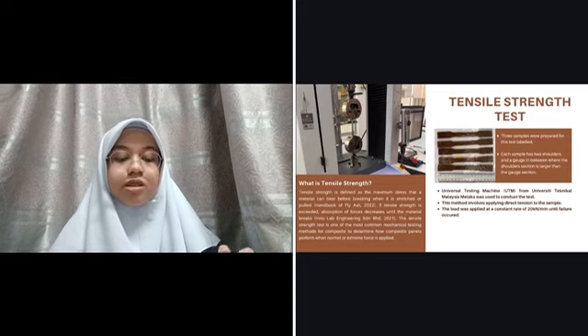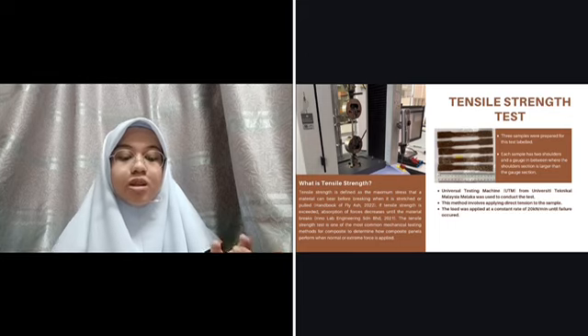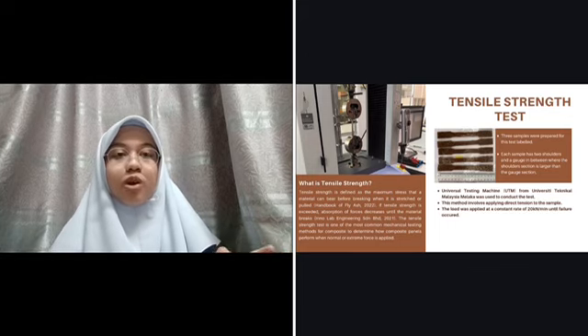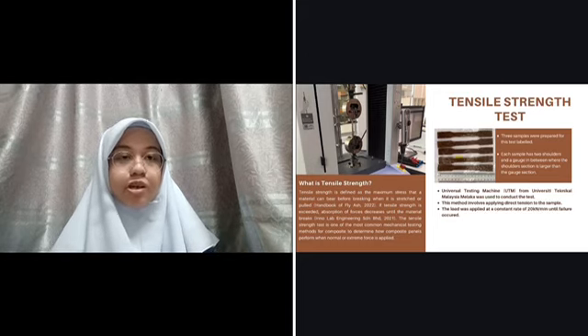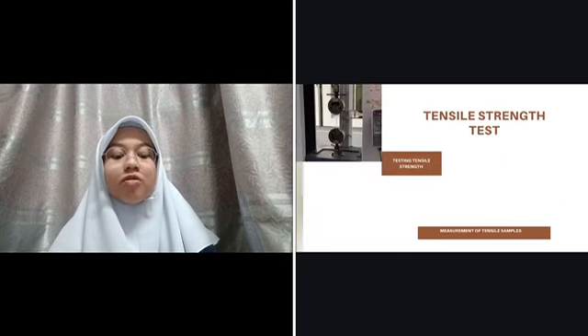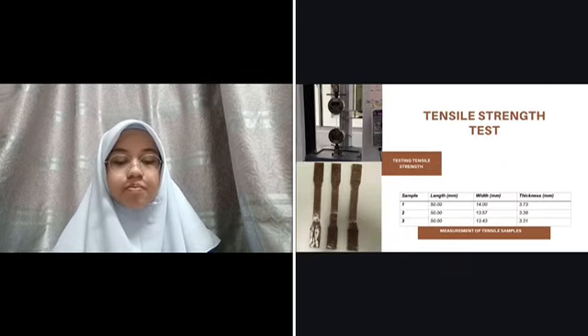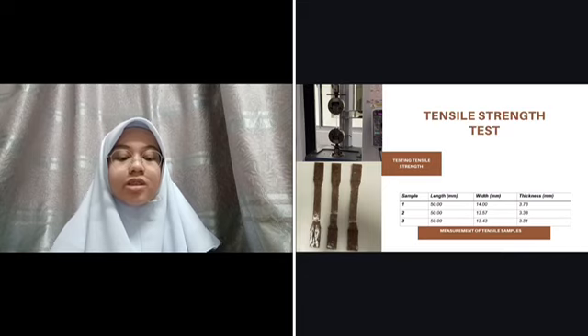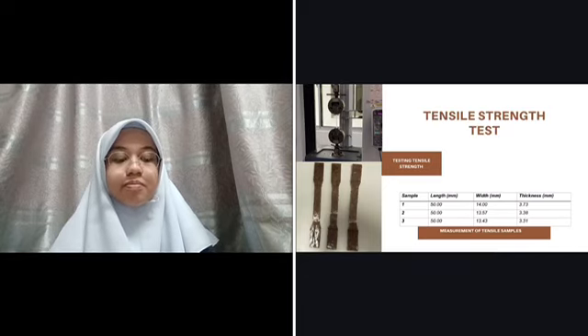So the universal testing machine will apply a load with a constant rate of 20 kilonewton per minute until failure occurred, when our sample will break when it can no longer bear the force that was applied to it. So here are the measurements of each tensile sample. As we can observe, the lengths of the samples are constant, whereas the width and thickness differ.